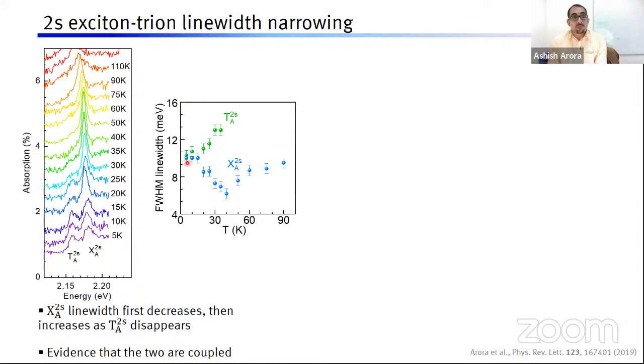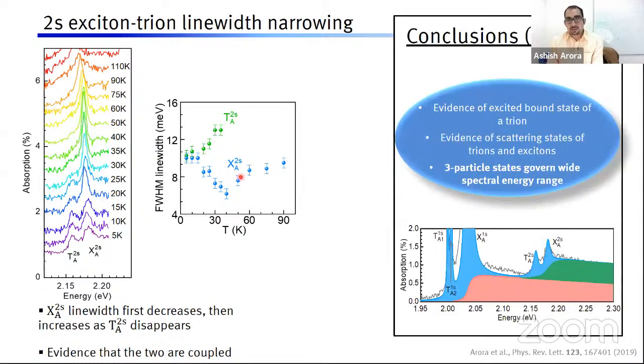Now, this is exactly what we see. For the trion, the line width keeps on increasing. However, for the neutral exciton, the excited exciton, it goes down when we raise the temperature. Now, in semiconductor physics, this is not very common. When we raise temperature, the line width goes down. But here, this is a piece of evidence that these two things are connected or coupled with each other, and one of them is a trion and one of them is an exciton.